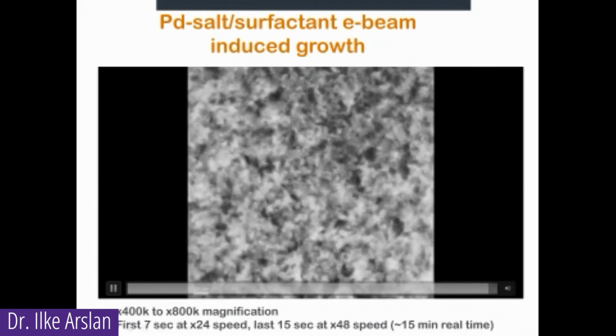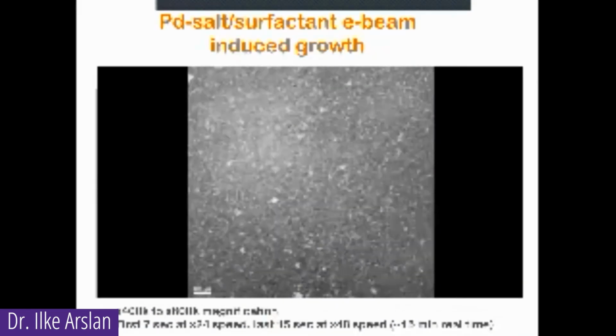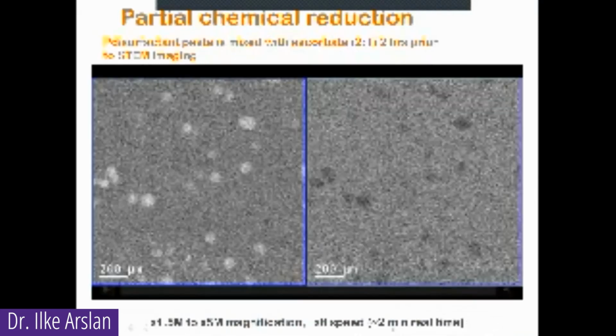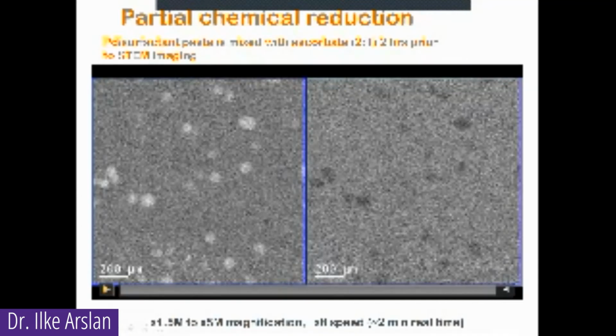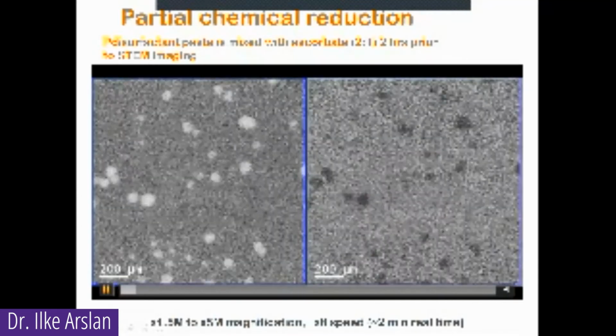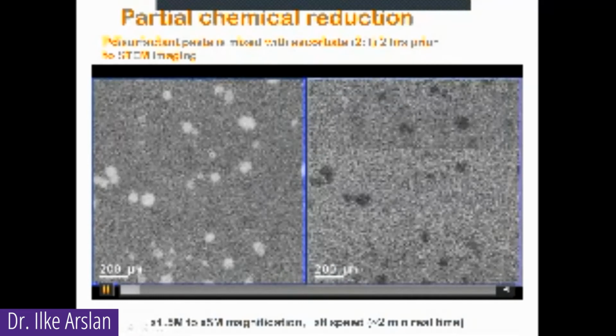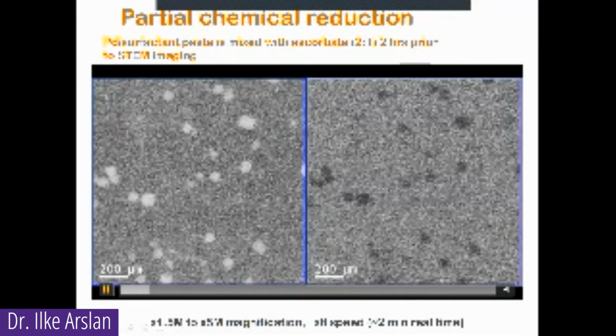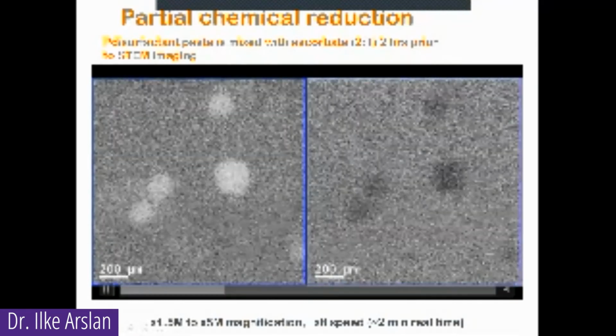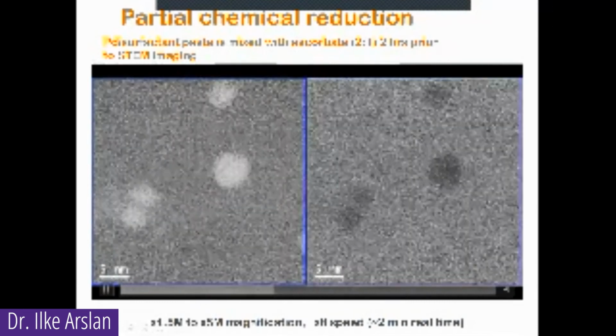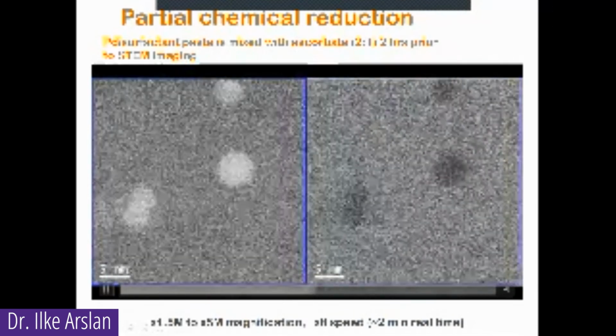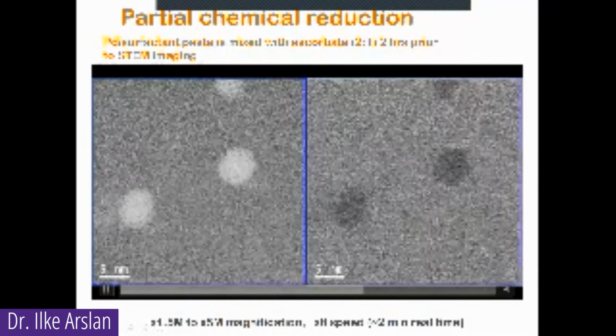So we formed a porous thin film, which is not what we want because we wanted to emulate the particle growth. So what we did was a partial chemical reduction to get it started in the right direction, and then we put it into the TEM. And now we start seeing what we really wanted to see, which is how do these porous nanoparticles form? We have 2.5 nanometer particles come together and form into 5 nanometer particles. These are the initial stages of growth.